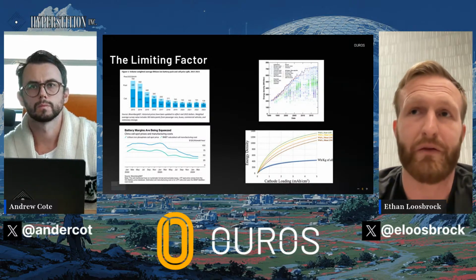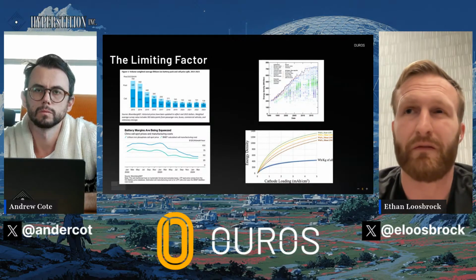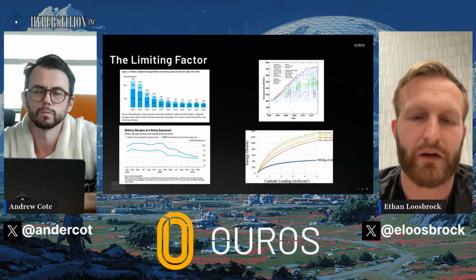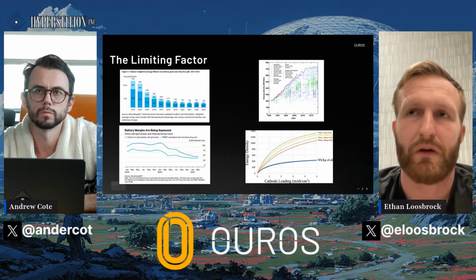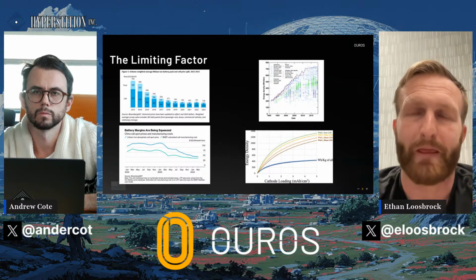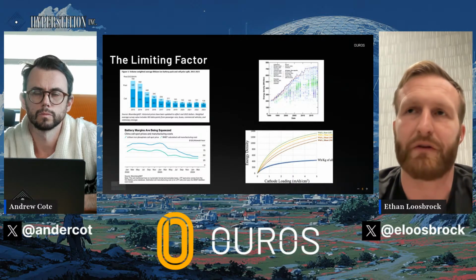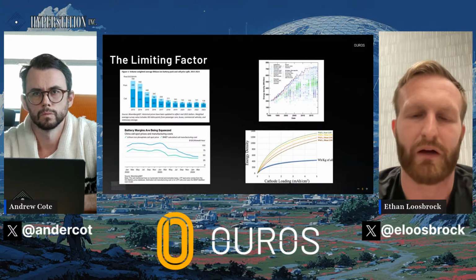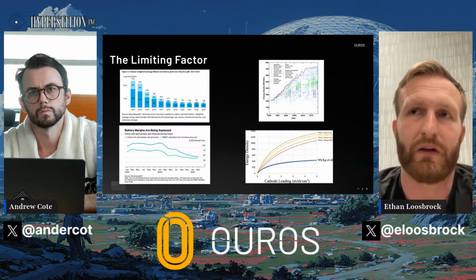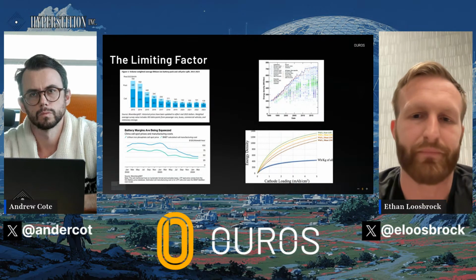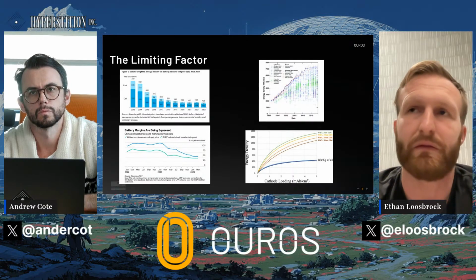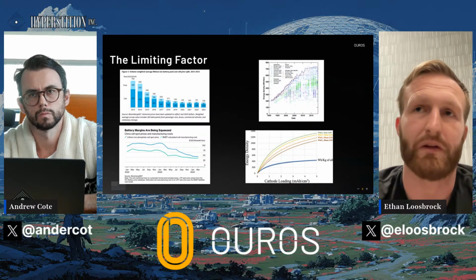Silicon, however, has been used in commercial cells for 15, maybe even 20 years now. Tesla has been using 7 to 9% silicon in their anodes for at least 10 years, and it works really well. The challenge was always swelling, but especially with companies like Sila and Group 14, that challenge has more or less been solved. With Group 14 and Sila, you can do 100% silicon-carbon with little to no swelling, and you can get 1,400 cycles with it. And it's 5 times the energy density, or capacity, of graphite. So you're at 1,900 milliamp hours per gram instead of 350 for graphite.